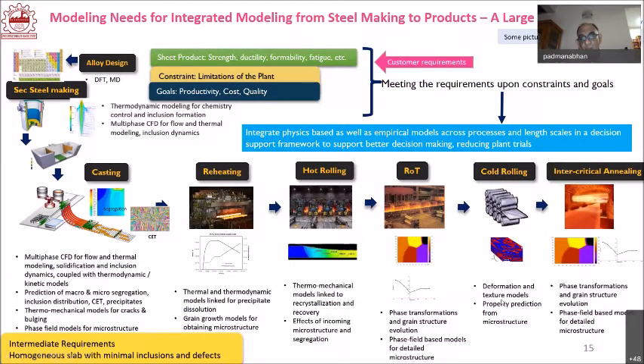Texture models can be done in two ways. One is the industrial approach, where they assume, as the deformation proceeds, the shape of the grains also changes proportionately. So this is the so-called pancaking or pancake approach. On the other hand, one can do it more rigorously through texture analysis, like what is being done by people like Samajhdar, Ranjit Ray, Satyam Suhas and others. There you see it is much more difficult to correlate the texture changes with properties. And some new methods are coming here, which a bit later I will talk about: crystal plasticity using discrete Fourier transforms. But then, again, these are statistical methods, and fundamentally, to predict the mechanical properties of two-phase materials from the texture is still a very big challenge.